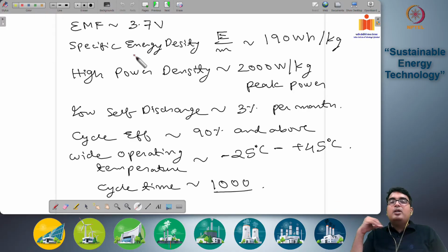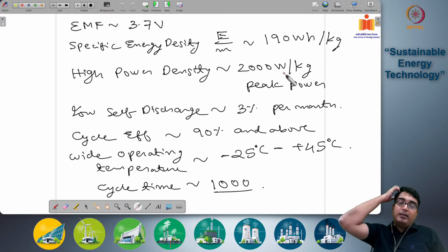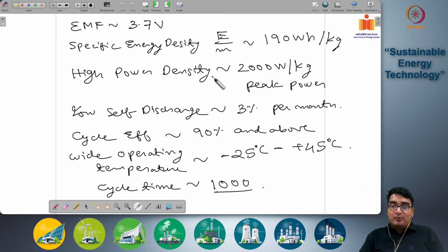Very high EMF values for these lithium-ion batteries, and it also has a very high specific energy density of 190 watt-hour per kg. These are actual specific energy densities, which are 3 to 4 times those found in lead oxide or nickel-based battery systems. It also has a very high power density of 2000 watt per kg as peak power. Remember that between energy density and power density there is a trade-off. If you get a peak power of 2000 watt per kg, at that peak power you won't get the same specific energy density as this one. But still you can get very high power densities along with high specific energy densities.